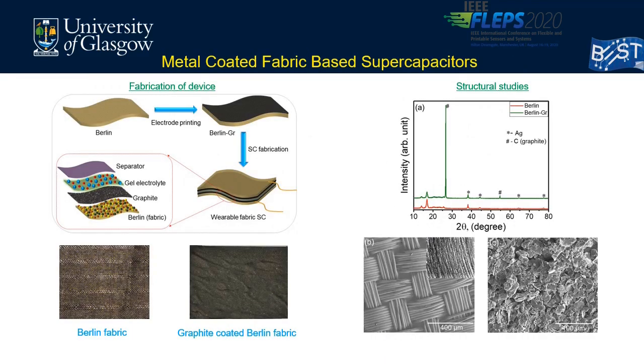Then we come to the present work, that is, the metal coated fabric based supercapacitor. From the previous analysis we came to know that the maximum operational voltage we can achieve for this nickel and copper coated textile is around 0.5 volt, because of the high redox reaction taking place on the nickel as well as copper. So in order to enhance the operational voltage, here we have selected silver coated textile, that is Berlin.